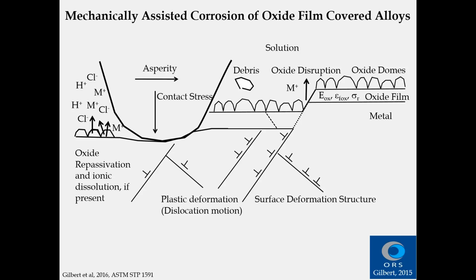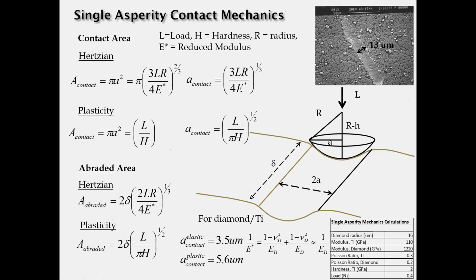Now, going back to mechanically assisted corrosion in oxide films, what we basically experience here is some hard contacting asperity inducing fracture and driving abrasion of the oxide. You could also have edges generated by dislocations where you disrupt the oxide, and the repassivation reaction happens immediately following, right behind that. You can get oxide debris formed as well as release ions, generate hydrogen, and all of the other myriad factors that we know go into mechanically assisted corrosion.